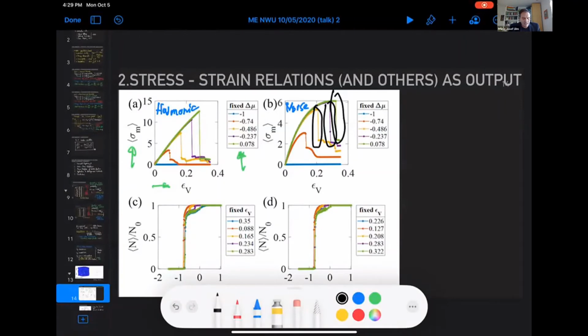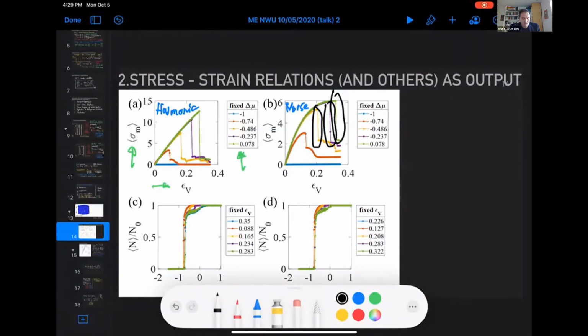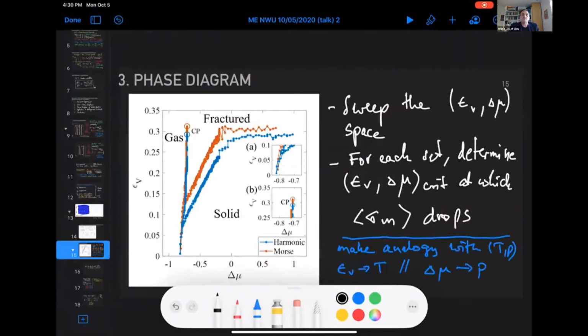And that's the idea of putting all this into a phase diagram. That's basically the idea of it. So we sweep, in essence, numerically, the volume strain and delta mu, so the (ε_v, Δμ) space here. And then for each set, we determine the critical value at which sigma m, so the stress, drops. And that's basically how the phase diagram looks. So you have on the one side the solid, so the uncracked system, and on the other side you have the fracture system.